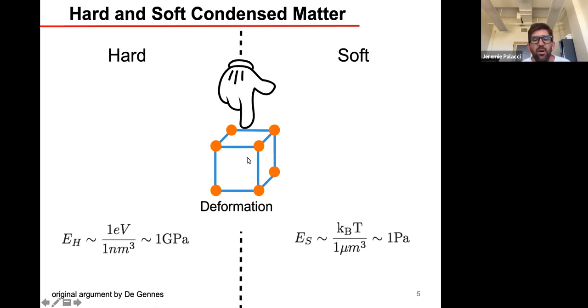So now if I consider the situation I just discussed for the sap, where the building blocks are like 1 micron and the typical interaction is kBT. So kBT is 1/40 of an electron volt. You can remember that as an order of magnitude. But most importantly, instead of having 1 nanometer cube, you now have 1 micron cube. So you can see that your volume has increased by a factor of 10 to the 9. And so as a consequence, you end up with a Young modulus, which is going to be of the order of a Pascal, which is very soft.